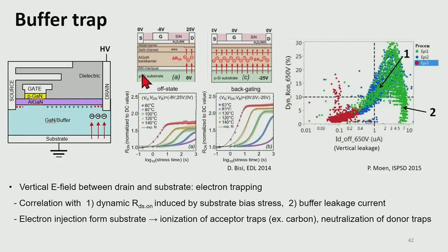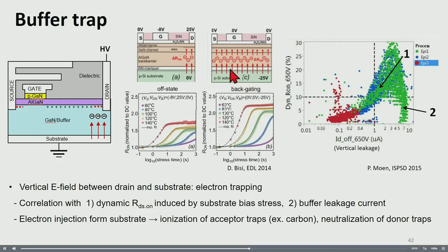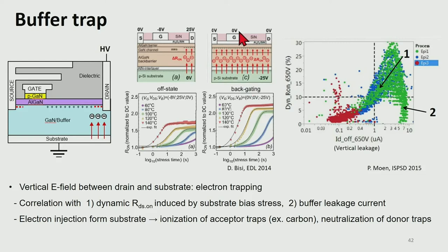Another important electron trapping mechanism in the off state is the electron trapping inside the gallium nitride epi. As you reviewed in the TDDB part, there is a vertical electric field between the drain side channel and the substrate. So electrons in the substrate can be injected into the gallium nitride and they can be trapped. To study this electron trapping mechanism, people typically use the backgating stress configuration. To replicate the drain side region of the standard device in the off state, you apply a negative substrate voltage while applying low voltage on the top terminals. In this case, the entire device is exposed to the vertical electric field, so the electron trapping in the gallium nitride epi can be amplified.